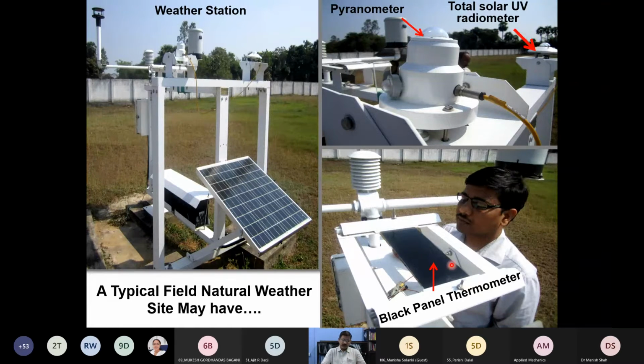But apart from that, when a black polymer, I mean the black geomembrane, is exposed to sunlight, for example, the annual average temperature of Chennai is very close to 35 degrees, but the temperature at which the polymer is subject to aging, because of the black body radiation effect, may shoot up to around 45 to 55 degrees and above. So that's why we have installed a black panel temperature sensor in order to measure the precise temperature of the polymer.